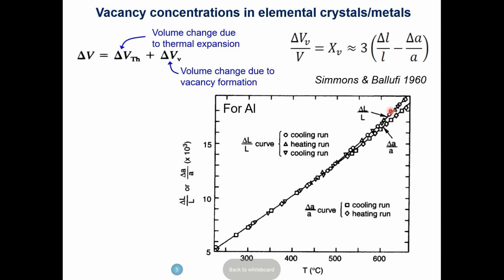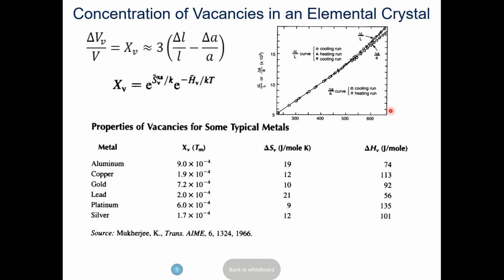So this sort of technique to estimate vacancy concentration works very well for elemental lattices, and here's some more data. You can eventually calculate not only the vacancy concentration, but also the entropy term and the enthalpy term, and this has been done for many metals. It's very reliable, very good data that we use for this.